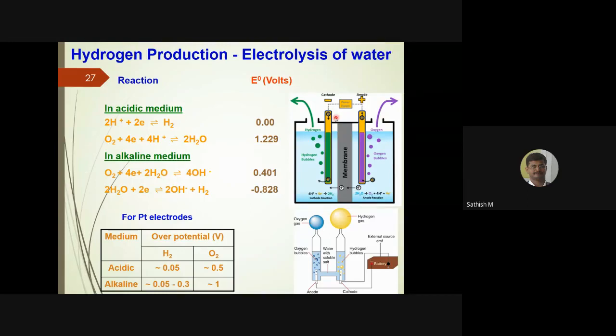The other one is electrolysis. You could do electrolysis in both acidic and alkaline medium. In the acidic medium, this is the reference potential, I hope you may be aware of it. This is 0 volt, whereas the oxygen evolution is 1.23. If you go for the alkaline medium, then it is 0.4, and your hydrogen evolution occurs at minus 0.8. If you add these two reactions, it will be 1.23 in both alkaline and acidic medium. You cannot do only one reaction. That is a main drawback.